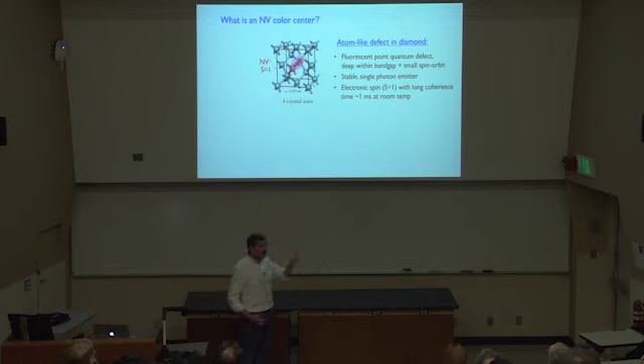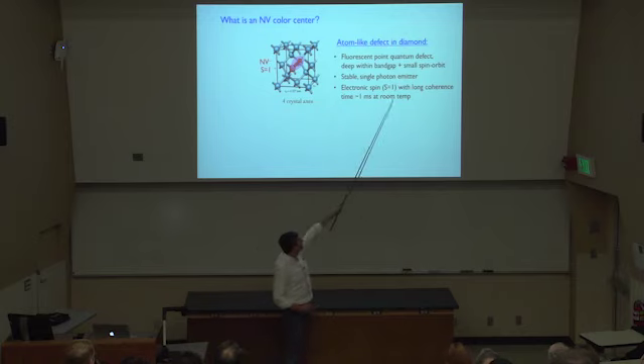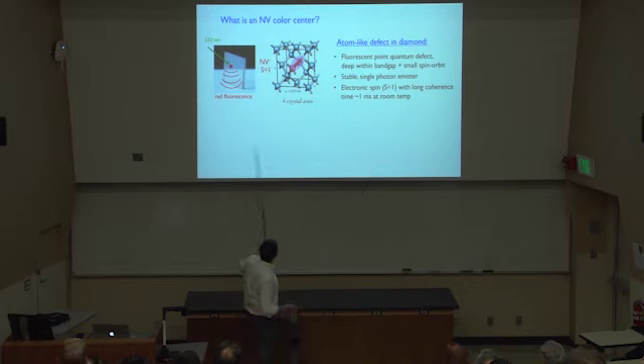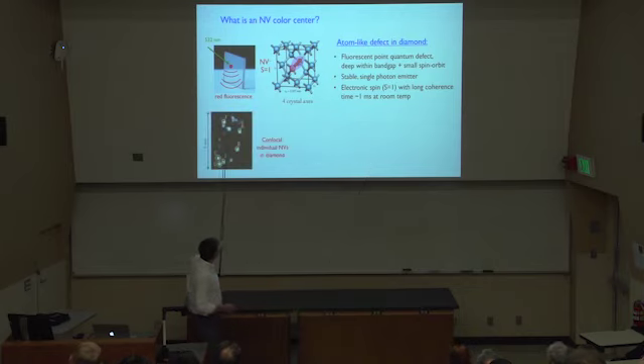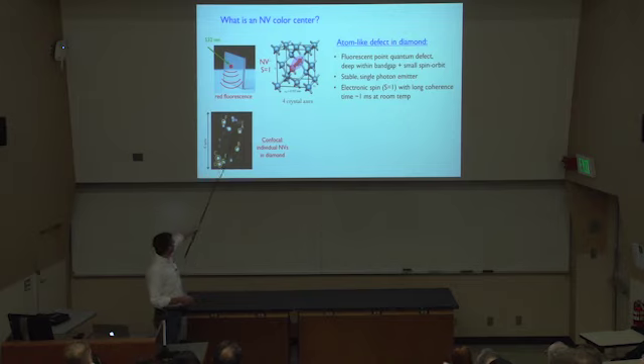Many other defects that exist don't all have these nice properties. Relatively small spin-orbit interaction, which is key for some of the energy level structure behavior that I'm about to outline for you. The long coherence times I've mentioned before. Here's that nice cartoon again. You can control your density of NVs in the growth process to be low so that you can look at one NV at a time and see that they are single photon emitters, and the photon correlation function, the G2 goes to 0 if you make the time go to 0, right, that sort of thing, and play with them